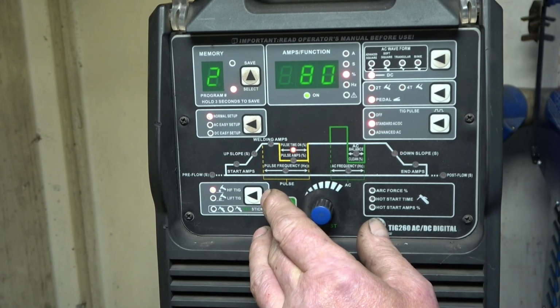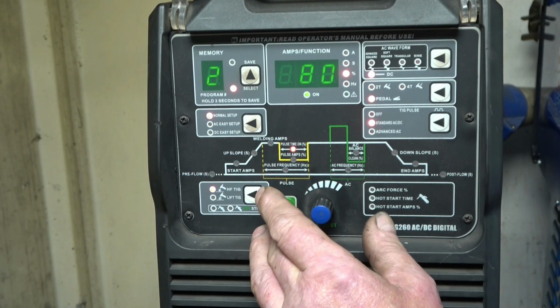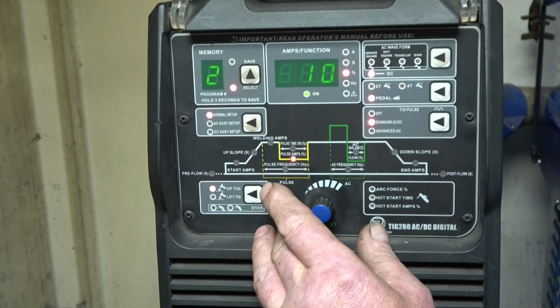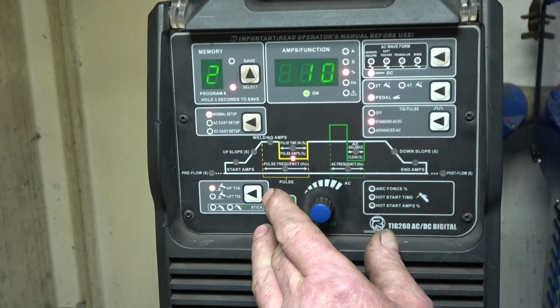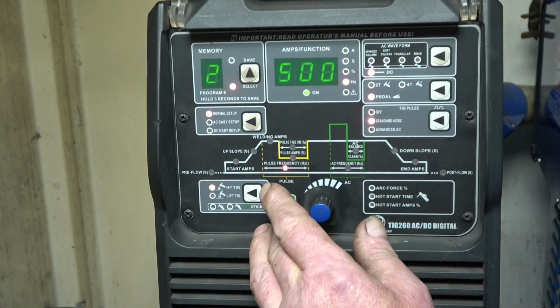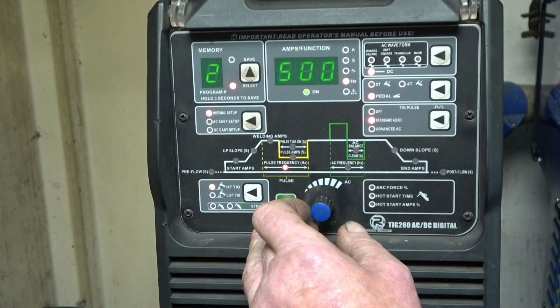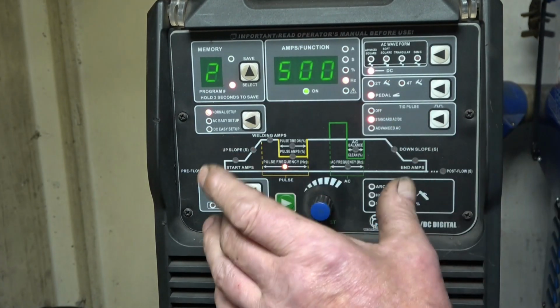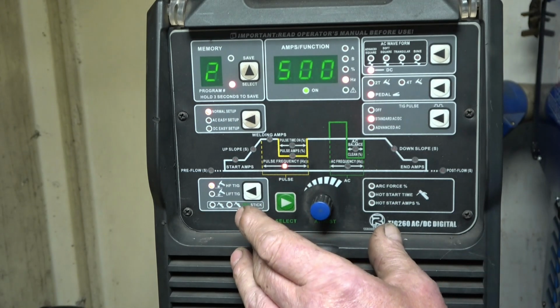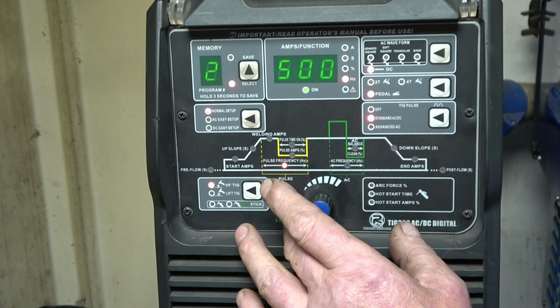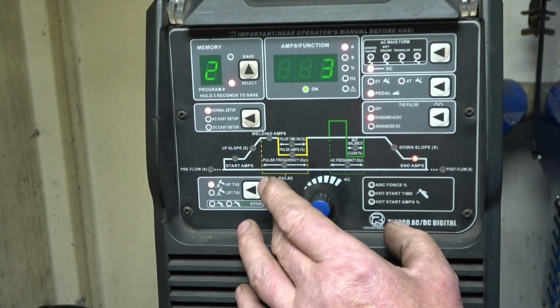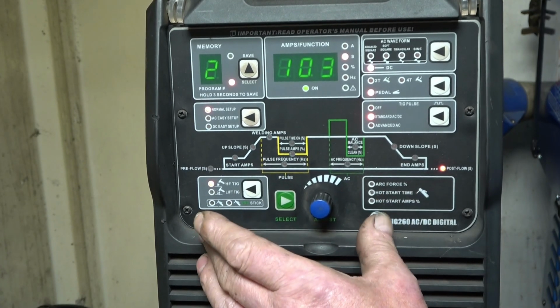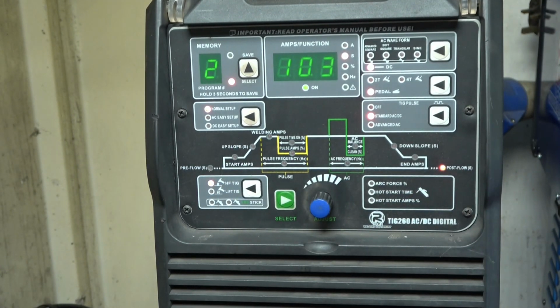That's going to be on for 80% of the time. For the other 20%, it'll have 10% of that amperage. That's going to happen 500 times a second. I've got that turned right up. I find the higher the pulse rate, the tighter the weld bead becomes. Once again, no pre-flow, no start amps, no upslope. And I've got 10 seconds to let the tungsten cool off.